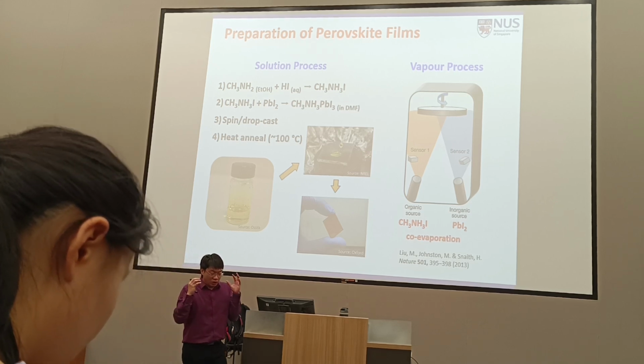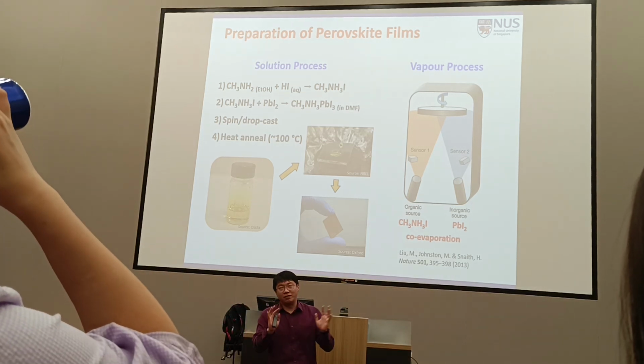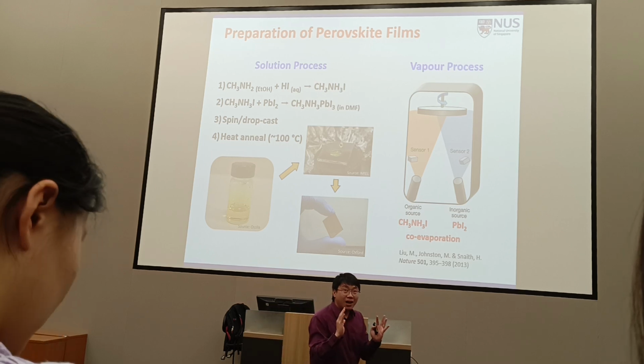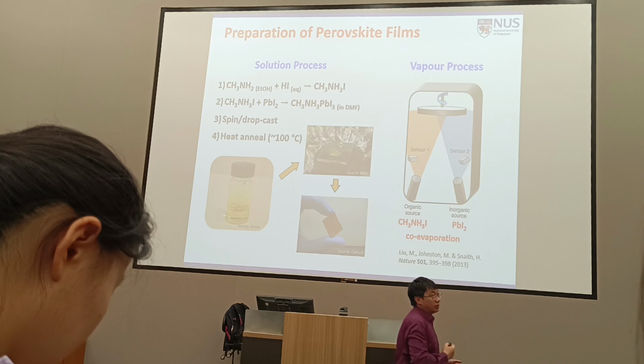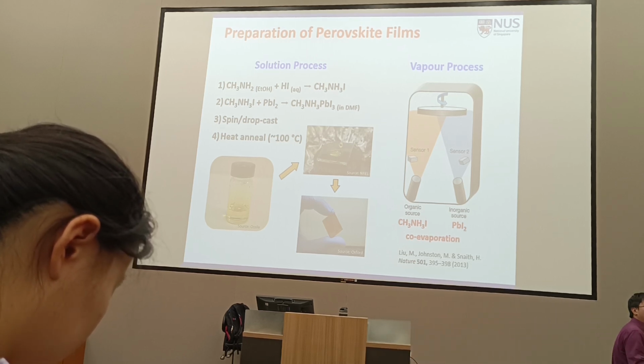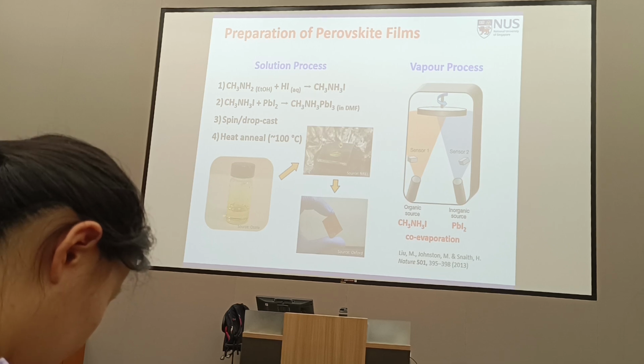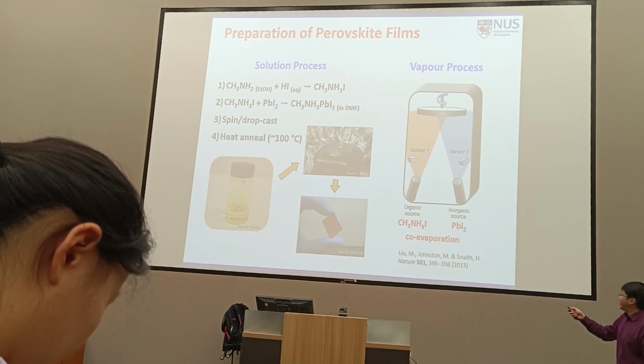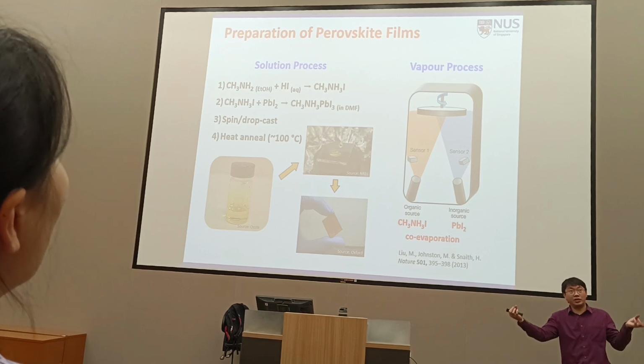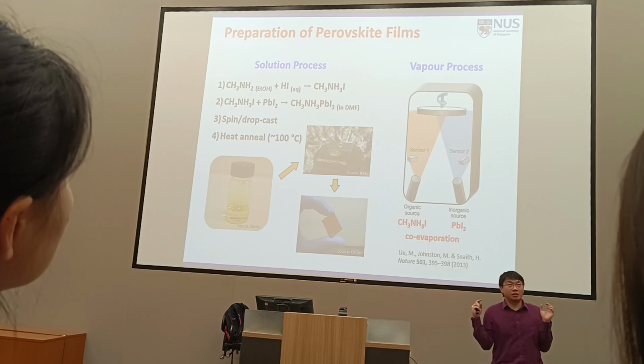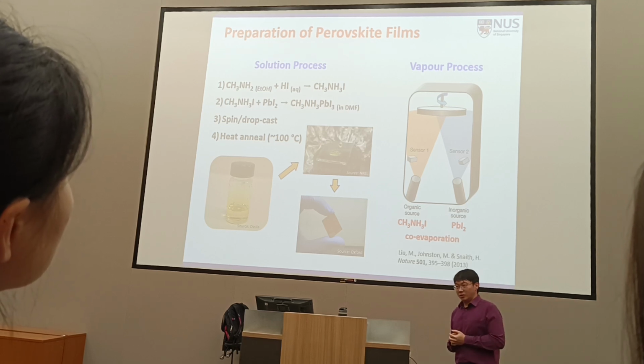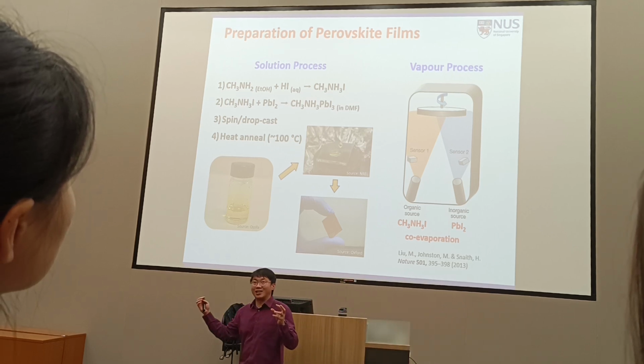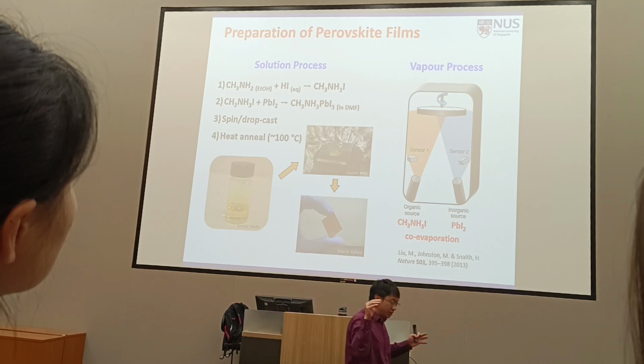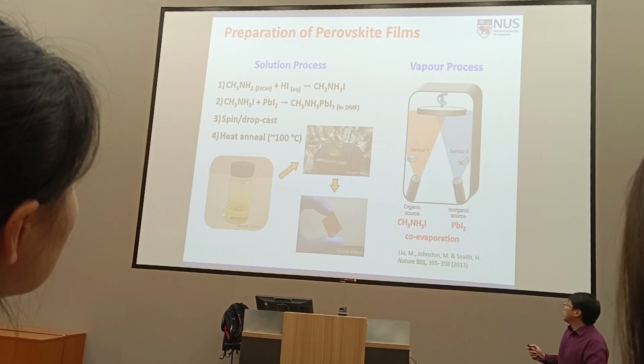Then you apply a vacuum to this entire chamber, so this chamber becomes a high vacuum environment. And we're talking about very good vacuum levels like 10 to the power minus 6, minus 7 millibars. Very, very low pressure. So now under very low pressure, I will heat up these two sources. And when that happens, the material evaporates. If you like, you can also call it sublimes. Sublimes means turning from a solid into a gas, right? So it sublimes.